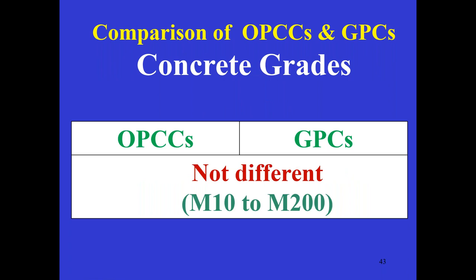Okay, concrete grades. Don't write any paper telling that geopolymer concrete is stronger than OPC concrete. Don't write such sentences anywhere because it is a question of mix design. For a particular case, you might have got lower OPC strength. Doesn't mean that it is better than geopolymer. No. So that's why I put here, we can have the grade changing from M10 to M200. M200 has been made at SERC laboratory by Dr. Anthony. And at SRM we went up to 70 MPa, which I was also having in SERC. So it is possible to use our particle packing theory and get strength up to 200. That is important. So it is not only the proportions, how do we reduce the pore content of the system? That is the packing theory.